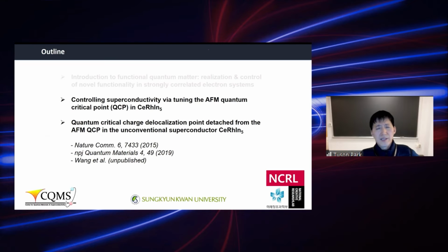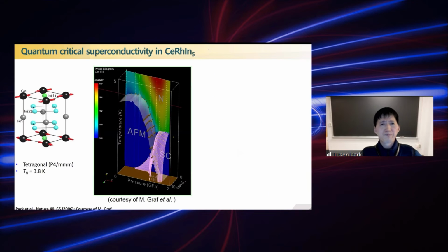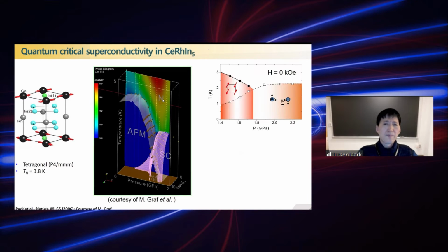CeRhIn5, the subject compound that I will discuss, is the ideal system to address those issues. CeRhIn5 forms in a tetragonal structure with cerium-indium planes stacked along the c-axis. And this is the three-dimensional phase diagram of temperature, pressure, and magnetic field, where the dome of superconductivity appears when the antiferromagnetic state is suppressed, and then the strange metallic phase appears in the normal state. This is a two-dimensional temperature-pressure phase diagram, and as you see, at pressures lower than 1.7 GPa, superconductivity and magnetism coexist together. On the other hand, at higher pressure, only superconductivity arises.